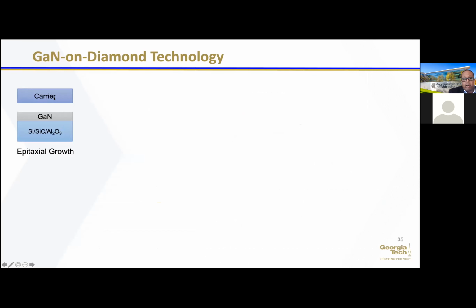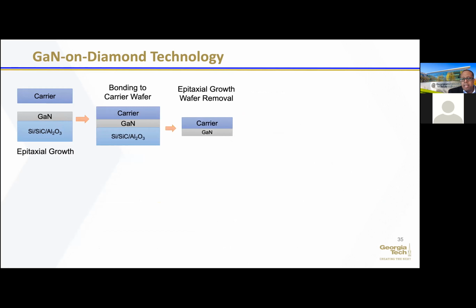Again, let's go back to our carrier wafer that I mentioned before. I have my GaN that's grown on silicon carbide or aluminum oxide. I'm going to bond it to this carrier wafer. And then what I'm going to do is remove it. So there are various techniques to remove the growth wafer. And then in one case, I'm going to place diamond seeds on the back, and I'm going to grow diamond on the back of the gallium nitride. This is probably the more common technique that you see with people that are producing GaN on diamond. And then you remove that carrier wafer.